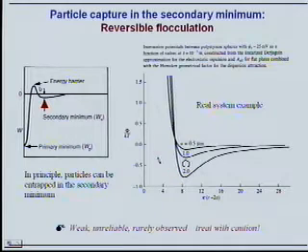And you can see actually the reason here. This is a theoretical calculation for these different systems. Now you are going to tell me why this secondary minimum is pathetic. It's less than kT. So particles entrapped in the secondary minimum are going to jump out by thermal motion.